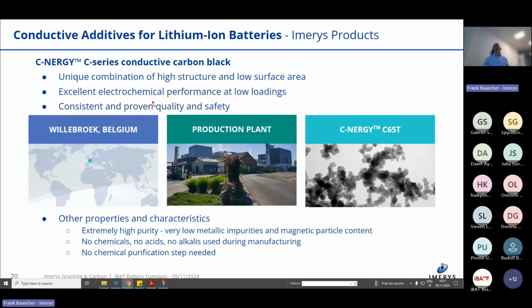And this is also very important. We see a lot of competition, especially in China today, trying to target our materials. The big challenge for all of those companies is to establish a reliable production where you constantly, at a 10,000 ton per year scale on a line, produce conductive carbon black of consistent quality and high purity. This requires a lot of experience. You cannot simply build a plant and hope that the product that comes out is good enough for lithium-ion batteries. Same as I said before applies to carbon black. We don't have to have a chemical purification process. So the way we operate our plant, the way we make carbon black delivers a high purity product so that no further chemical purification is required.